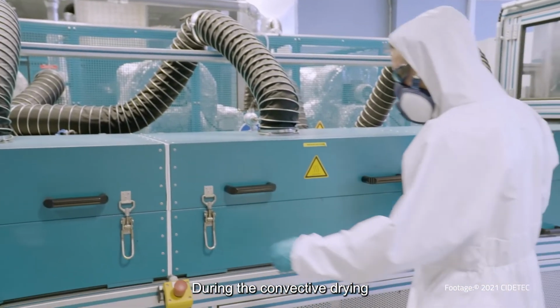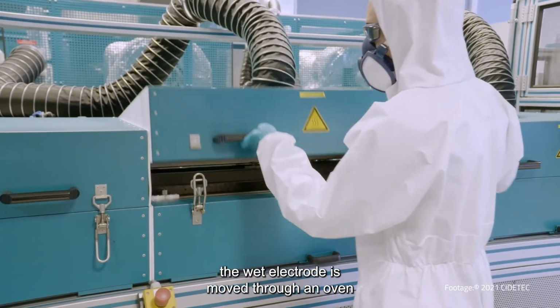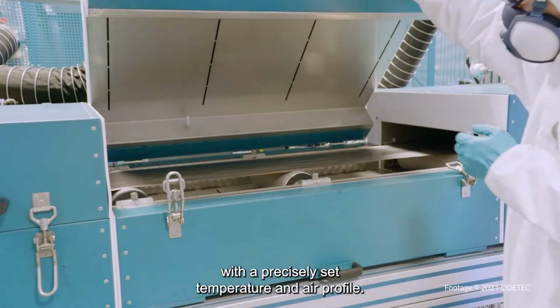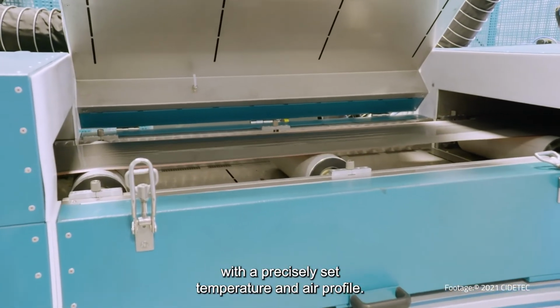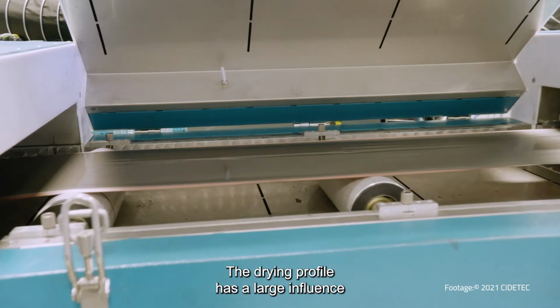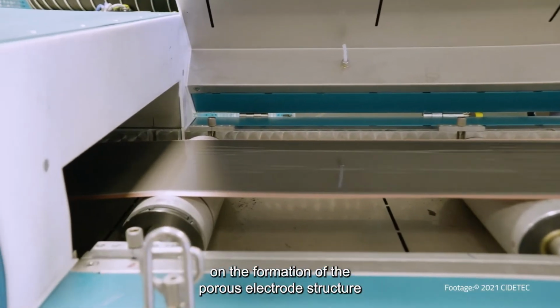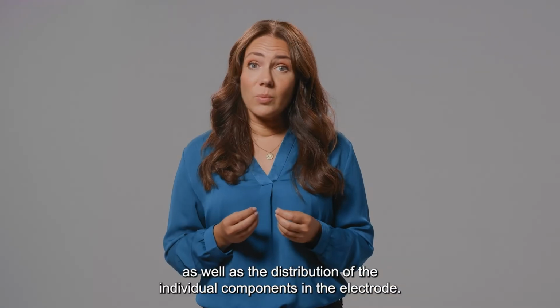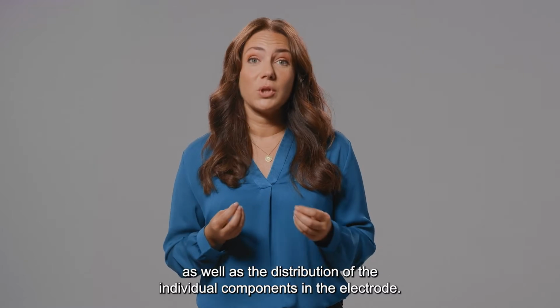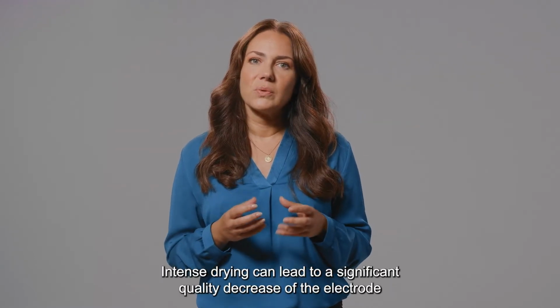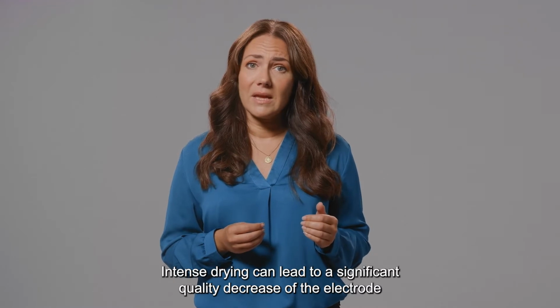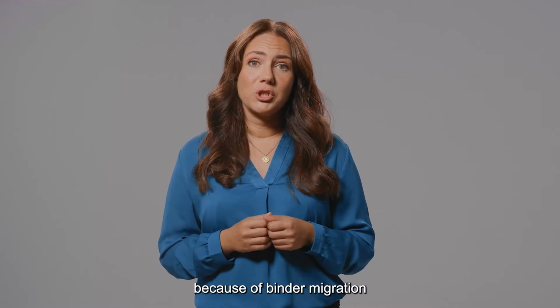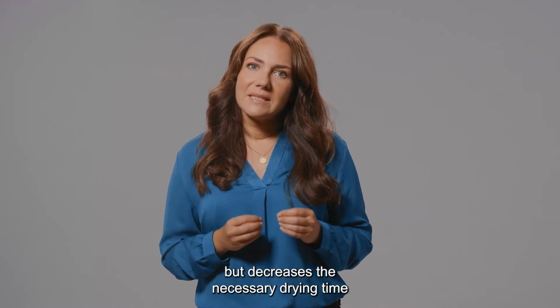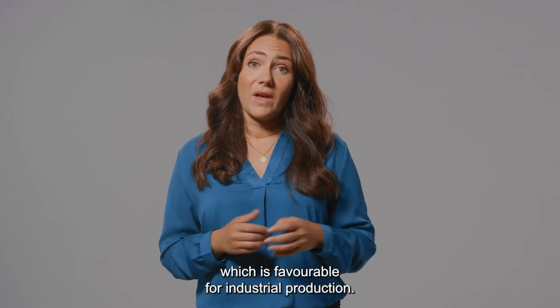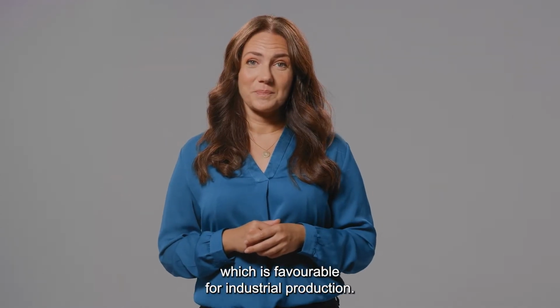During the convective drying, the wet electrode is moved through an oven with a precisely set temperature and air profile. The drying profile has a large influence on the formation of the porous electrode structure, as well as the distribution of the individual components in the electrode. Intense drying can lead to a significant quality decrease of the electrode because of binder migration, but decreases the necessary drying time, which is favourable for industrial production.